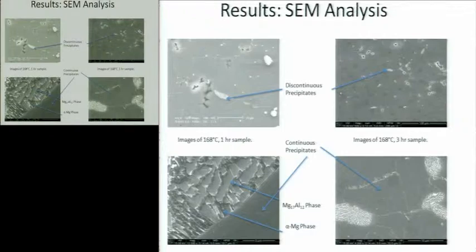If you look at the bottom 1 hour sample, you can see that the discontinuous growth, as I said before, are alternating plates of the alpha magnesium phase and the magnesium 17 aluminum 12 phase. And you can also see a small amount of continuous precipitates in the 1 hour sample. You can also see more of them in the 3 hour sample. So now I was able to see just from 1 hour and 3 hour that there was an increase in both discontinuous and continuous precipitates in both samples.